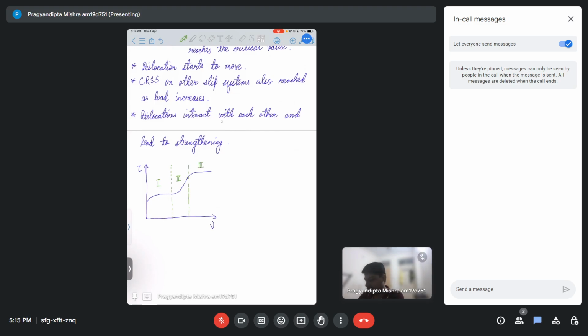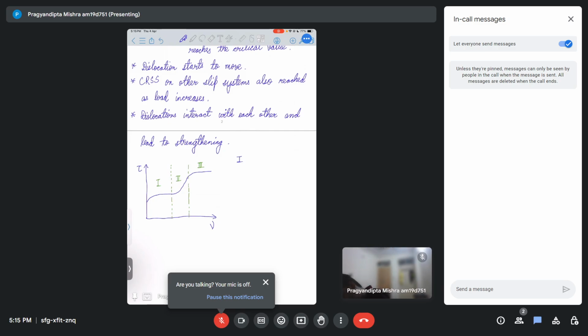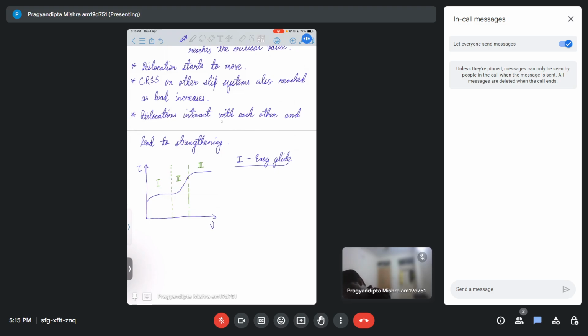Okay, so let's understand each stage one by one. What is exactly happening at each stage? In the first stage we will have easy glide. Stage 1 is called easy glide. So in this what happens? The very first step happens. The slip system with the lowest CRSS will get activated, and it will lead to negligible strain hardening, as only the lower CRSS slip systems will get activated. Essentially only those particular slip systems will get activated, and strain hardening will be very minimal. It will be more like dislocation starts moving, so the glide will happen. So easy glide will happen essentially.